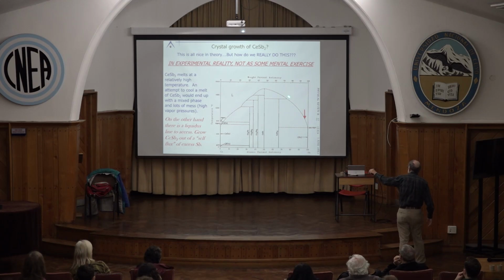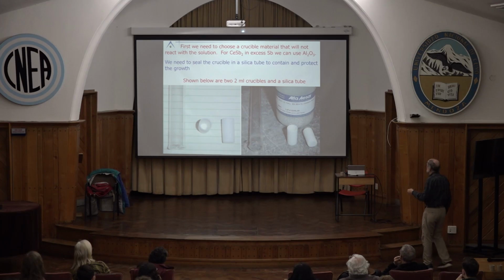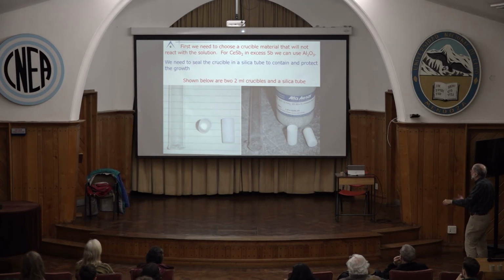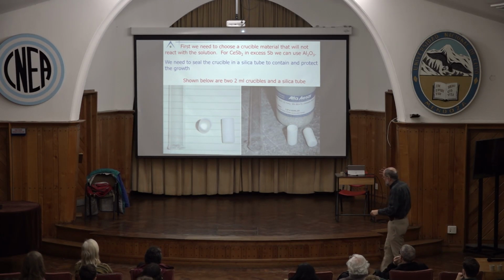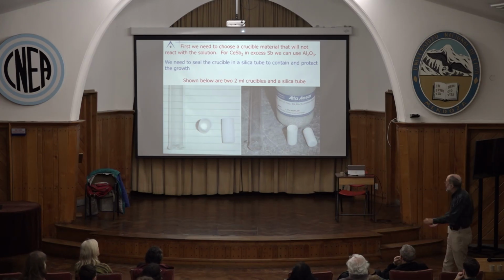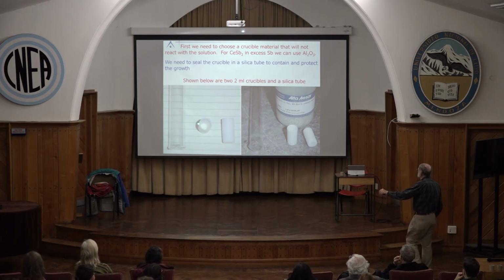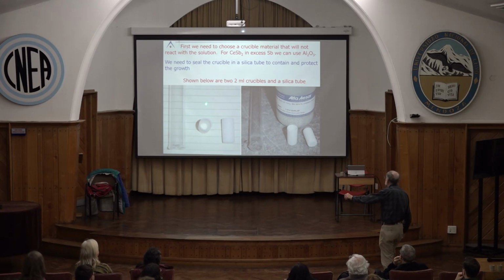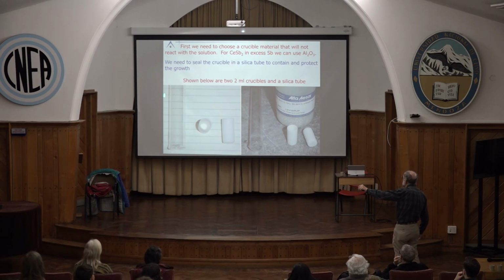Here we have the liquidus line for cerium antimony 2. I'm going to hit it here out of excess antimony so I can grow crystals. What's involved? Well, I need to hold this molten cerium antimony liquid in something. My hand doesn't work. So, I'm going to use an alumina crucible. This is polycrystalline sapphire, if you want to think of it that way. I have an alumina crucible, and I'm going to have to protect these from air, so I'm going to seal it into a silica, amorphous silica tube.